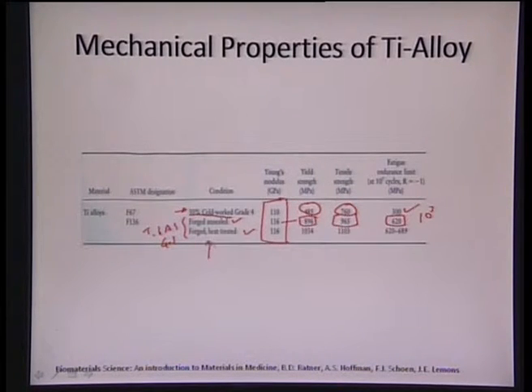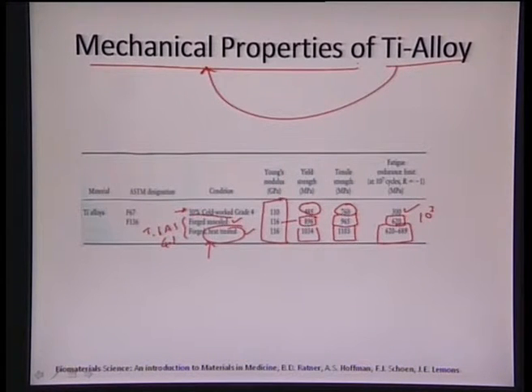Again, controlled heat treating can increase its yield strength to around 1034 megapascals, which is more than a gigapascal. Tensile strength is also increased to a certain extent, around 1.1 gigapascals, and fatigue strength is also increased to a certain extent. So we can see how the role of heat treatment can be utilized in the processing of titanium alloy to achieve enhanced mechanical properties. So that is what it is. Like titanium alloy, we are seeing certain properties.